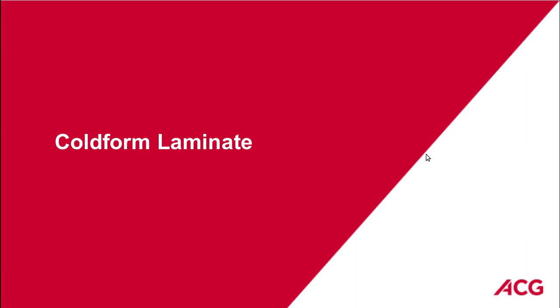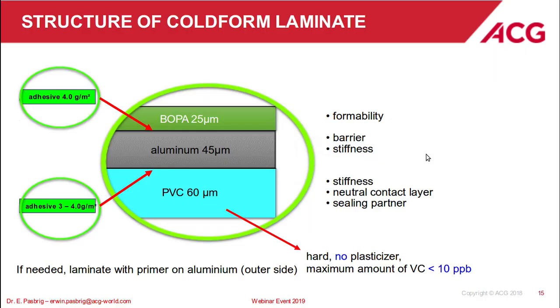Coming now to the cold form laminate. We see here in general the structure of cold form laminate. We have a sandwich structure with aluminium in the middle. On the outer side, we have biaxially oriented polyamide, 25 micrometer usually. On the inner side is the sealing layer, in our days still mainly 60 micrometer PVC. OPA is needed for the formability, aluminium as the metal gives the barrier and some stiffness for the laminate, and PVC as a sealing layer has to be neutral to the pharmaceutical product. It provides stiffness as well and is a sealing partner for the lid foil.